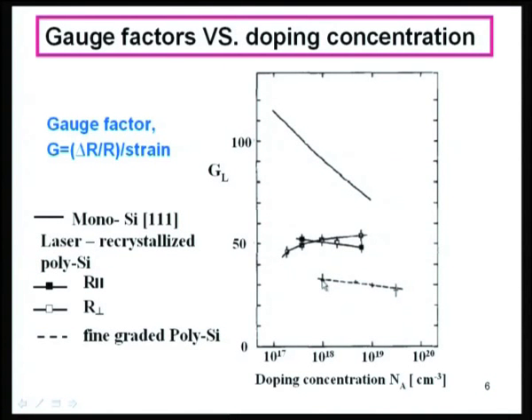In single crystal you can see, as you increase the doping, the sensitivity will automatically fall. Now, you take polycrystalline material, subject it to laser annealing, that is heating with laser, then the grain size will become bigger, the gauge factor goes up. If the grain size becomes infinite, it is single crystal. So, larger the grain size, better the gauge factor, that is what is implied by this. What we are sticking to is this polycrystalline material as deposited, whose grain size will be something like 0.1 to 0.3 micrometers. So, there will be a number of grains on the surface. Gauge factor is low. As I mentioned, nothing to worry about that.